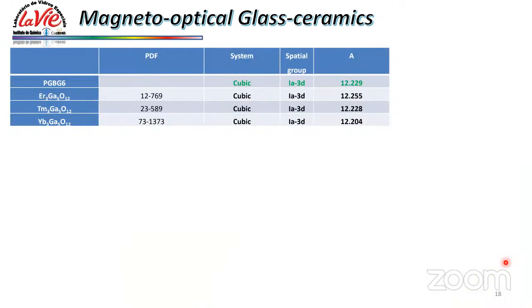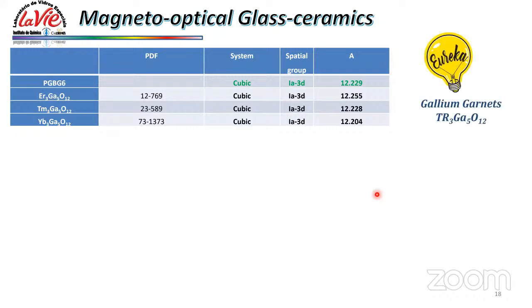And then when we characterized these crystals, we got some composition. The composition is similar to those of gallium garnets. So it's a rare earth gallium garnet. Here are some compositions that we can find in the literature. In our case here on the glass, we have the same kind of structure, the same space group, and in fact, we got a gallium garnet.